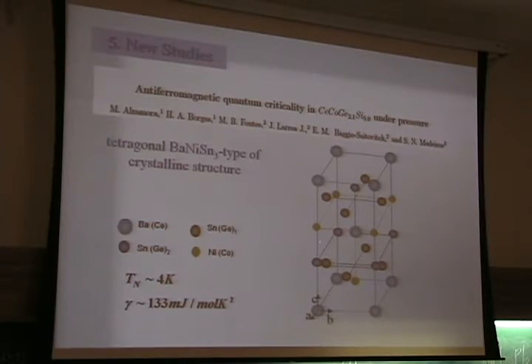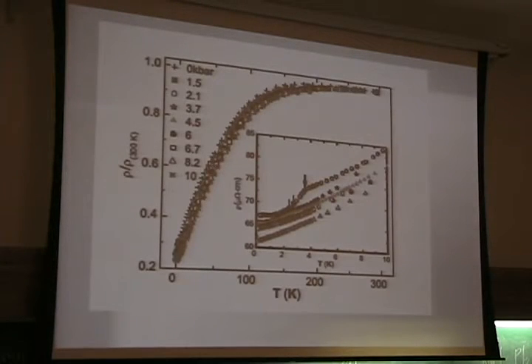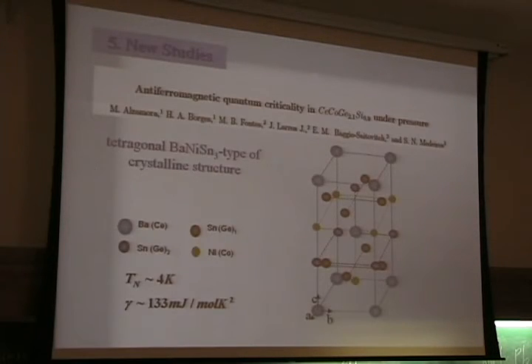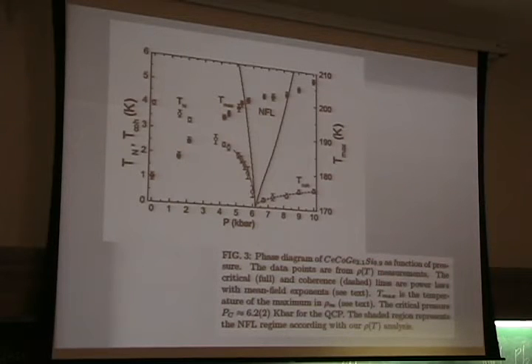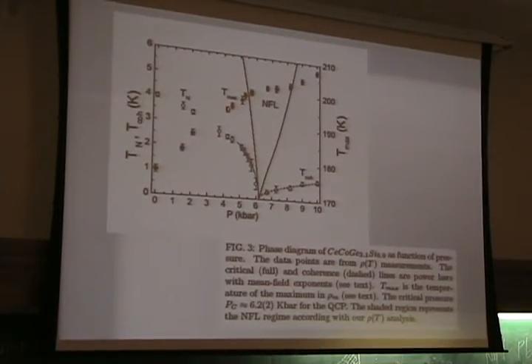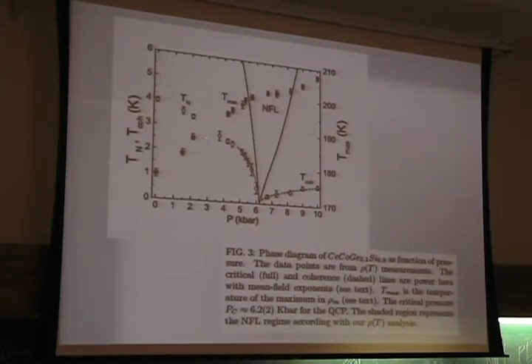And for this doping, it has a Néel temperature of 4K. It's also a moderate heavy fermion, and here is the transition temperature. As you apply pressure, again, you go to a linear behavior here, at low temperatures. Here we could very nicely build the phase diagram for this system. You see TN and T coherence, and also the T maximum, and this is the phase diagram.